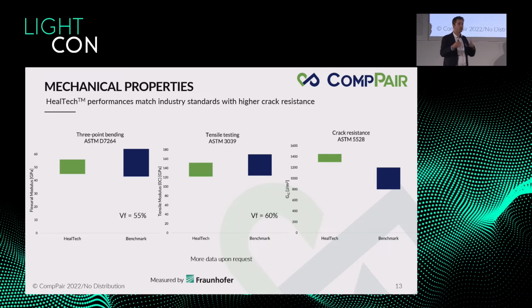Of course, it depends to what you compare to. If we are getting the comparison with ultra-high modulus and performances for resin into the space domain, for some of them, we are not competitive at all, but we have strategies to do that. But if you look at the benchmark and really traditional one, we are really meeting those benchmark, and those are ranges on this graph. And for crack resistance, so toughness, we are in average 30% higher than what you may find for traditional composites.